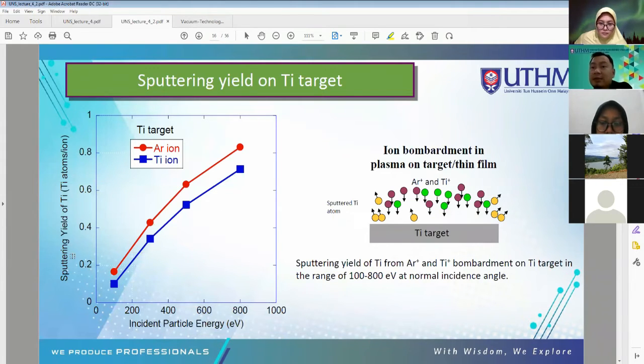So this is the result showing the sputtering yield of titanium. Sputtering yield is a number where we try to understand, when one ion hits the target, how many atoms will be released. That's why you see the unit is titanium atom per ion. If the sputtering yield is 1, it means one ion hits, one atom is released. If the sputtering yield is 0.5, it means one ion hits, nothing is released yet; the second ion hits, then an atom gets released. If the sputtering yield is 2, it means one ion hits, two atoms are released. This is what we call the sputtering yield.